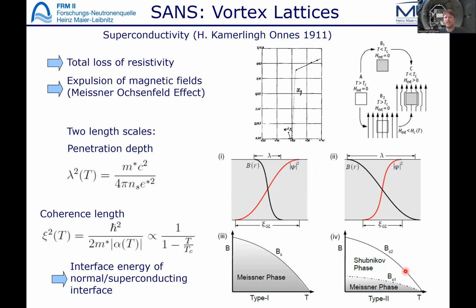So, superconductivity. That's a phenomenon which is actually quite old, about 110 years old. It was discovered by Kamerlingh Onnes in 1911, and is characterized by two effects. First, you have the total loss of resistivity, which we see here when the resistivity of mercury is plotted, and you have the critical temperature here of 4.2 Kelvin, where the resistivity drops down to 0.